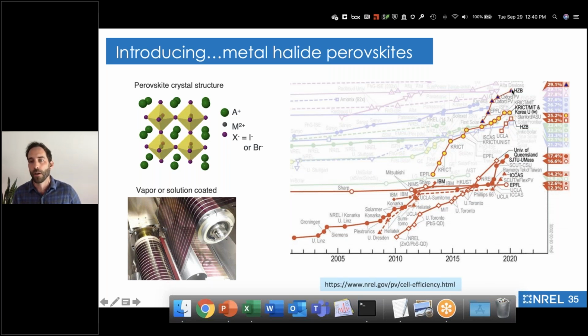And the last line I'll talk about here, and this is really a side, is the top line you see here. This is where you have the blue diamond, or the blue triangle with the red outline. It's increased up to 29%, so better than silicon. That's what happens if you put perovskite on top of silicon. You make what's called a tandem solar cell, using two different absorbers. So perovskites have really made people excited.